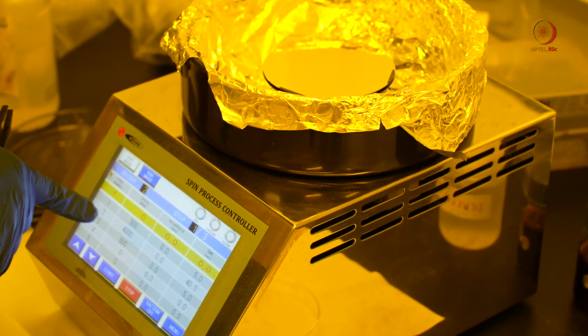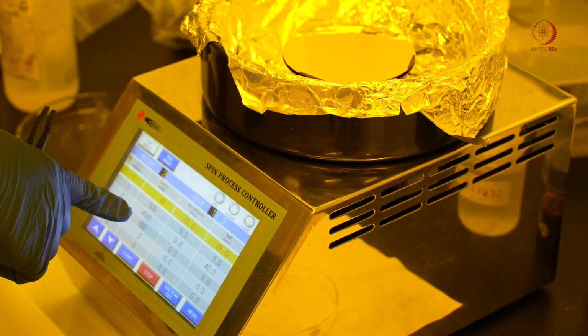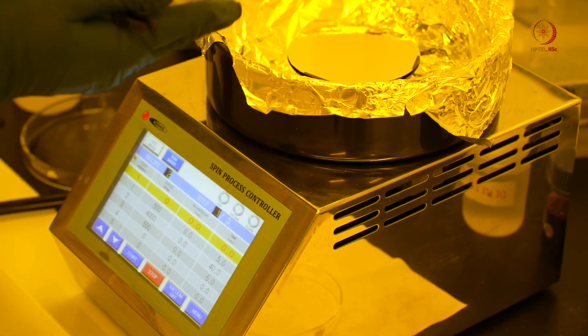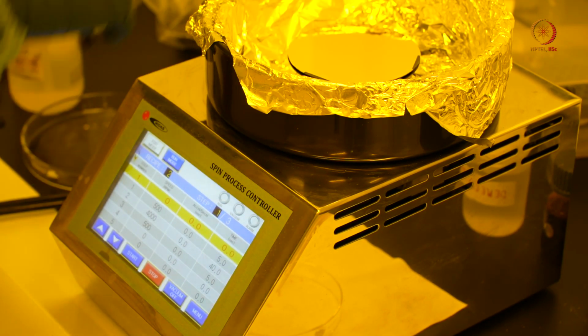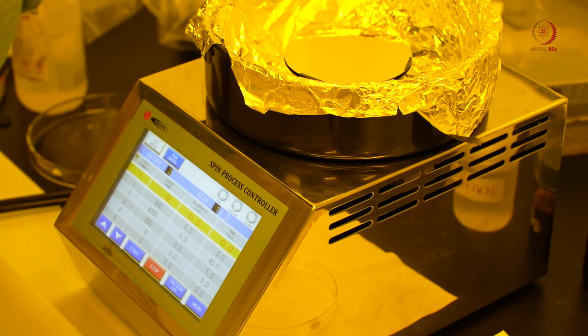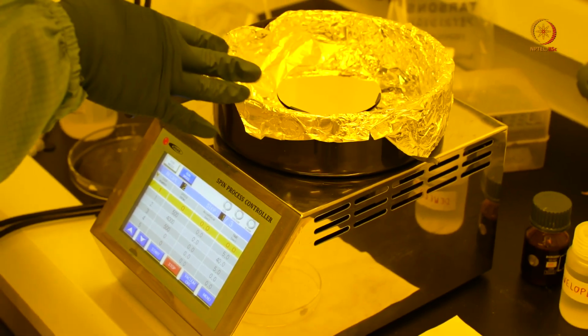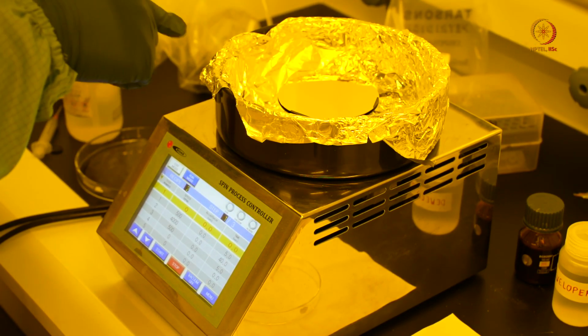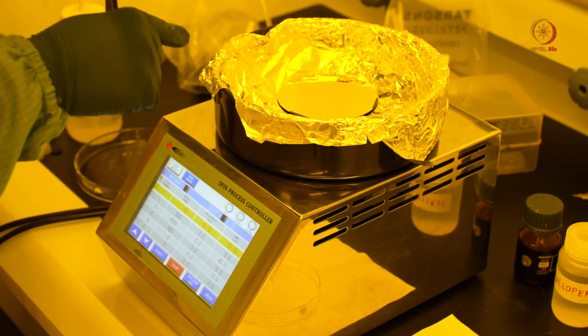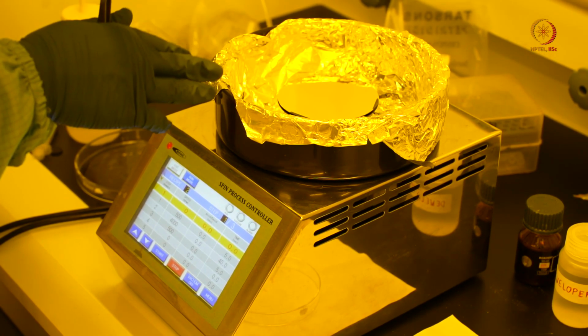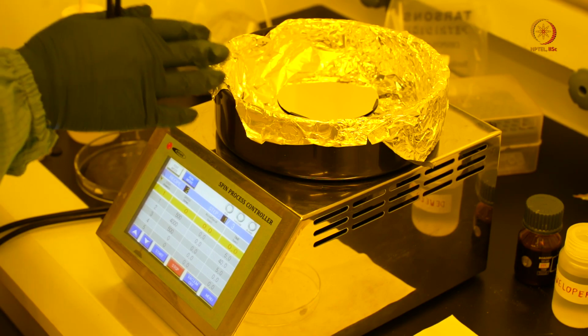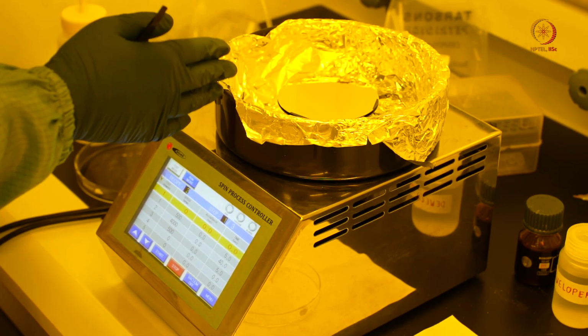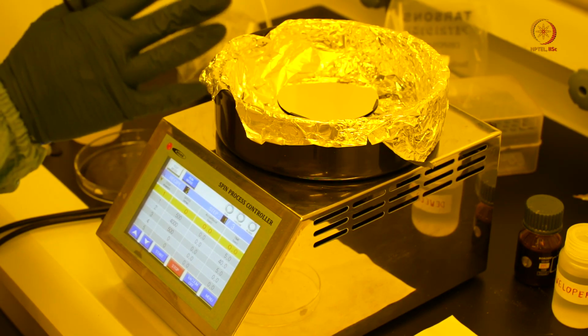We have already a recipe set, based on the data sheet that we have for the photoresist. We have to spin coat the photoresist at around 4000 rpm for around 40 seconds, and since we are using the 3012 positive photoresist, we rotate at 4000 rpm for 40 seconds so that we will get a thickness of around 1.2 microns.